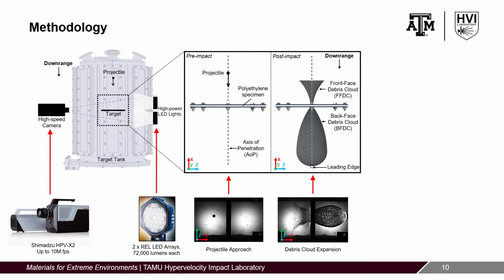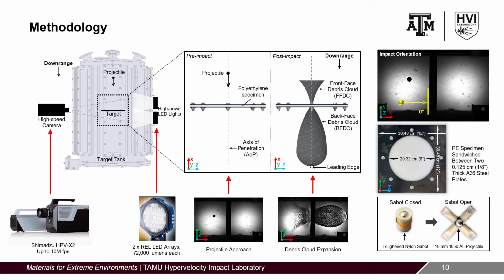Qualitative analyses of the impact event images were used to determine the material response, for example, target fragmentation versus target melt. Motion tracking software was used to determine the velocity of the leading edge of the back face debris cloud as a means to quantify the hypervelocity impact performance for the 2 candidate materials. The target specimens are sandwiched between 2 A36 steel plates, each having a cutout in the center, effectively inducing axisymmetric boundary conditions on the polymer specimens. The target assembly is fixed rigidly in a target fixture, such that the axis of penetration is aligned with the center of the target specimen.